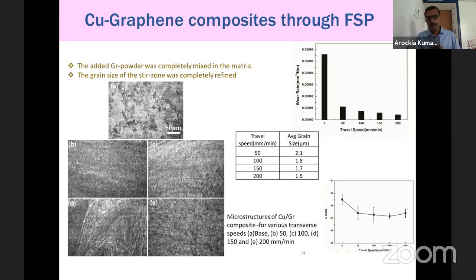And the good thing we have got through this research is the decrease in electrical conductivity. I am sorry for the poor graph here. The electrical conductivity in the as-received state is very close to 99% IACS. After incorporating graphene and refining the grain, the electrical conductivity is around 97.5, so around 1.3 to 1.5 IACS decreased. That is, the decrease in electrical conductivity is very small. But the wear rate is drastically reduced after FSP, and hardness also increased. So through FSP, we improved the strength significantly, at the same time there is an insignificant change in electrical conductivity. To an extent, our objective is achieved by employing the FSP technique.